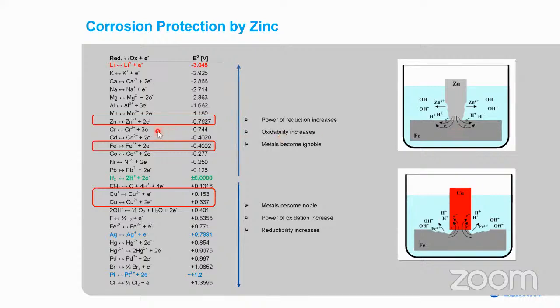The particular metal, as mentioned, is zinc. Zinc is available in large volumes. It is fairly cheap and therefore perfectly suitable to be used as corrosion protective pigment. If instead of zinc we would use a metal that is in the electrochemical series more noble, for example copper, the adverse effect would occur. The copper would remain in place and iron would oxidize away. As we don't want this to occur, today we will talk about zinc as a corrosion protective pigment.